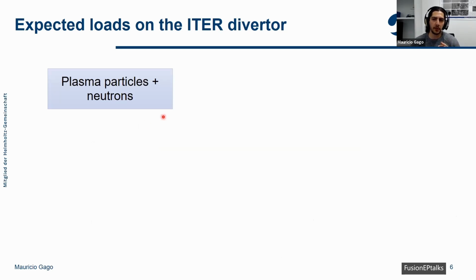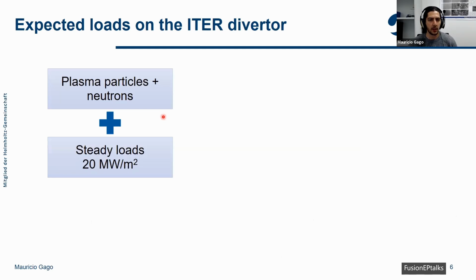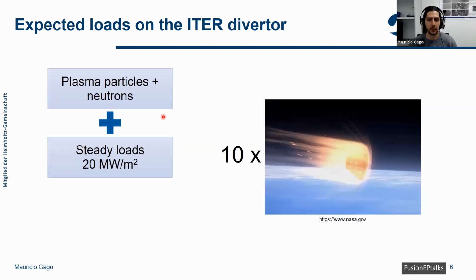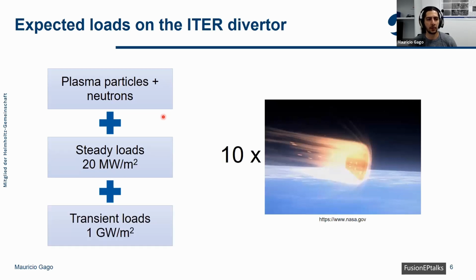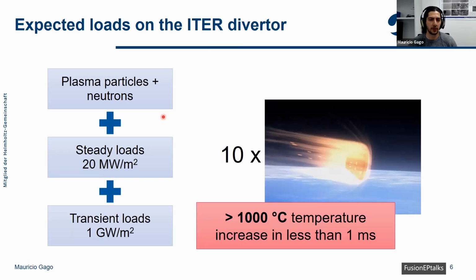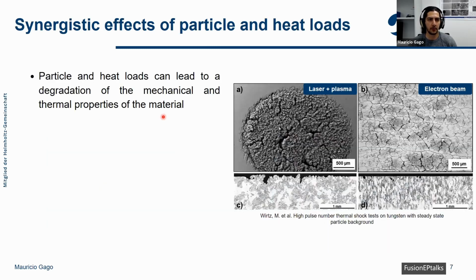I like putting these numbers into perspective. First of all, we will have highly energetic neutrons and plasma particles that can modify the lattice structure and the composition of the material. Aside from this, the steady state loads produced during normal operation in ITER will subject the divertor to up to 10 times the loads as in a spaceship re-entering Earth. And additionally, we will have the transient loads that I mentioned before from the ELMs, which will increase the surface temperature by more than 1,000 degrees in less than 1 millisecond. These are very, very high loads that we're expecting the material to sustain.